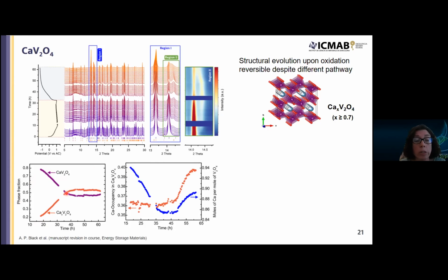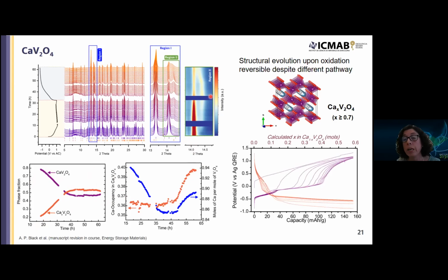This is just the phase fraction of the pristine and oxidized phase, which of course one decreases and the other increases upon oxidation, and upon reduction you see that the amount of each phase stays more or less constant, despite we increase the amount of calcium in this oxidized phase, in agreement with the formation of a solid solution.